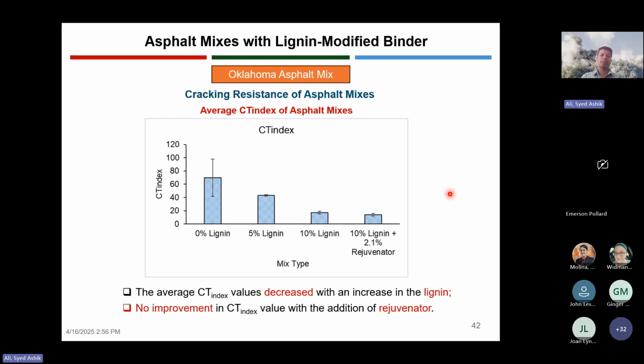So what is it doing to the CT index, or the cracking resistance? This is one of the things that we have found: as the lignin amount goes high, the CT index value goes down significantly. Although between 0% and 5%, because of the variability of the results, they may not be significantly different, with the addition of 10%, it went down pretty significantly.